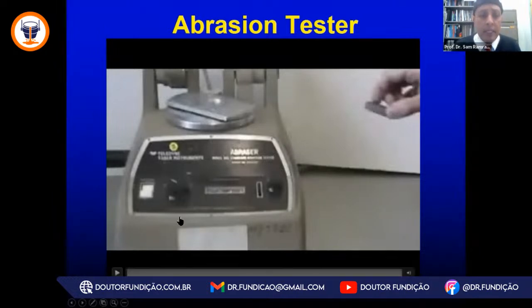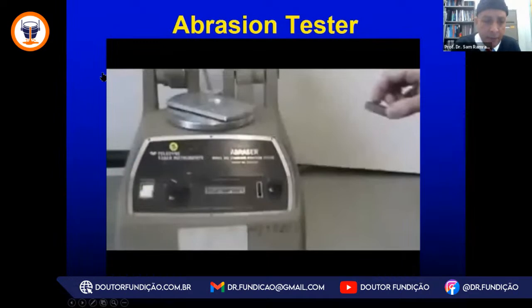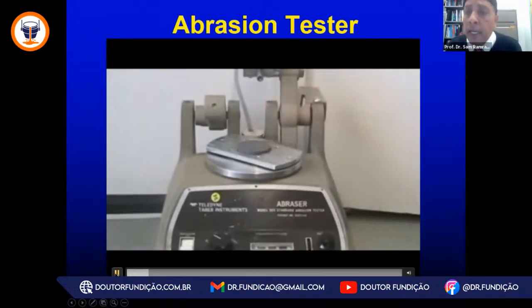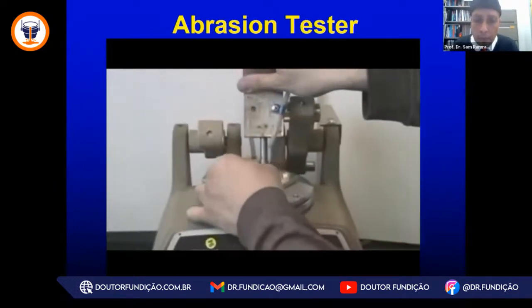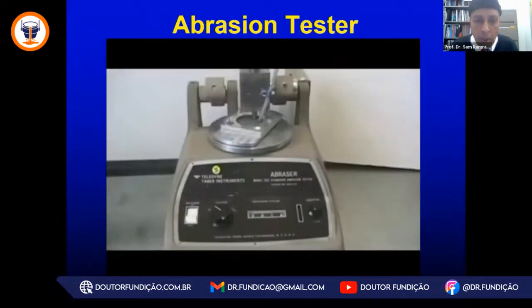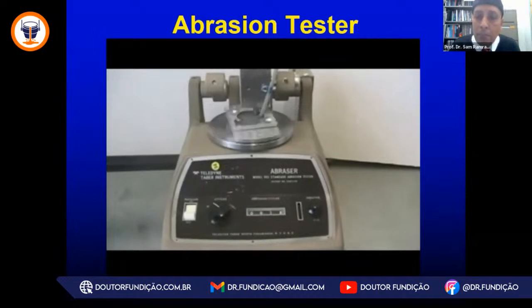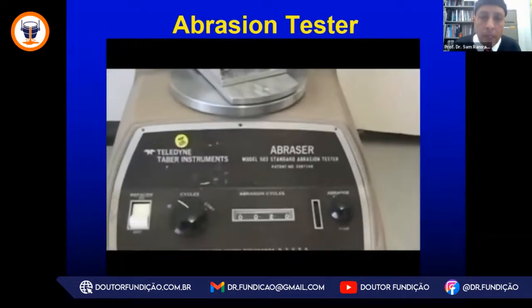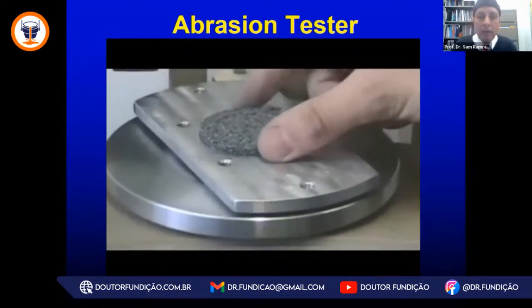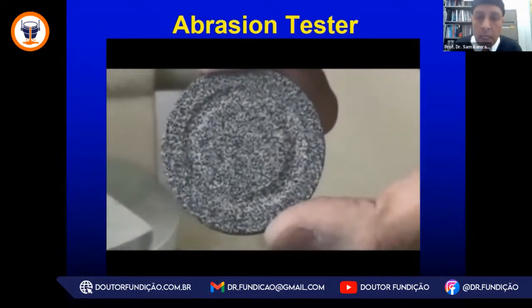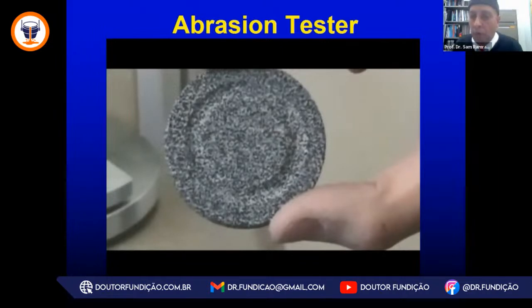Another new standardized test is the abrasion test, where we look primarily at the cure of the sand. This is basically the idea of an operator rubbing his or her fingers on the sand mold and core. So we have a ceramic ball, a hardened ball loaded with 200 grams, and that basically rotates 20 rotations as we draw by vacuum the debris at the cure, and that would reveal abrasion loss. We can measure the depth of loss, and that depth of loss is directly related to mechanical or other physical and chemical properties of the chemically bonded sand. Again, it's a good indication for degree of cure on the specimen.